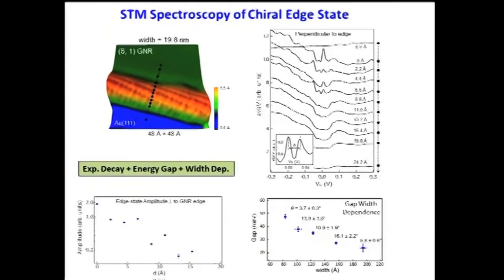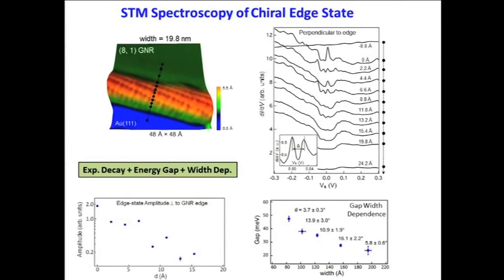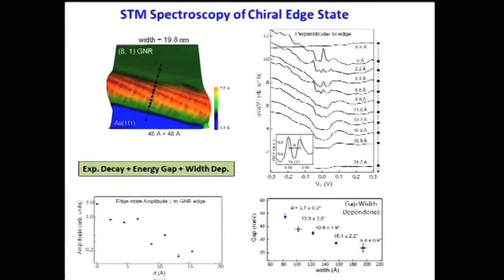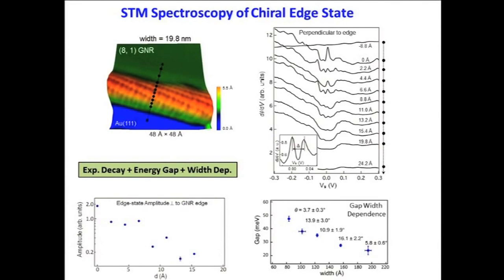is that we see two little peaks. Sometimes they're asymmetrical, but we see these two little peaks. Here you can see a close-up, so you can see these two peaks. And we believe that this indicates that there's an energy gap in the edge state, where the energy gap is the energy difference between those two peaks. We measured this behavior on many different nanoribbons, and we saw that for different widths of nanoribbons, we got a different energy gap. Here I show that data. We see that the energy gap gets bigger as we decrease the width of the nanoribbon. So we see a 1/width dependence on the energy gap of this edge state.